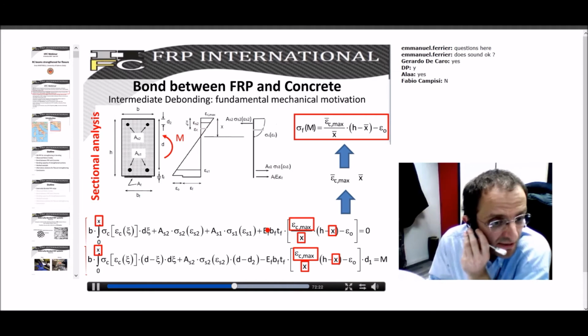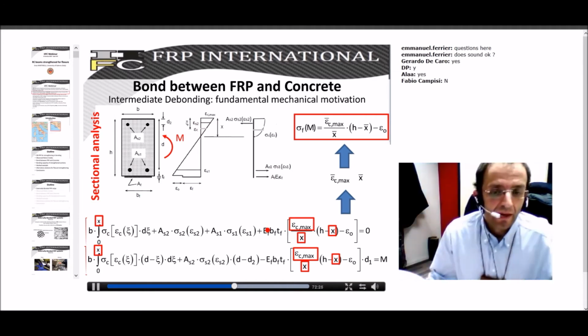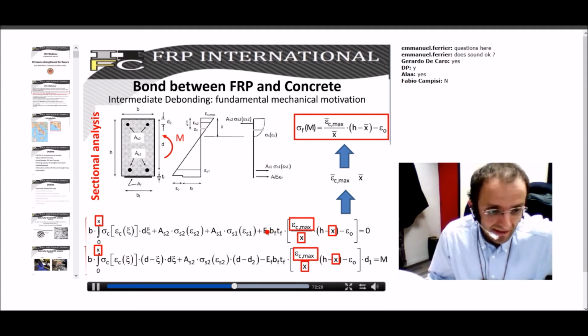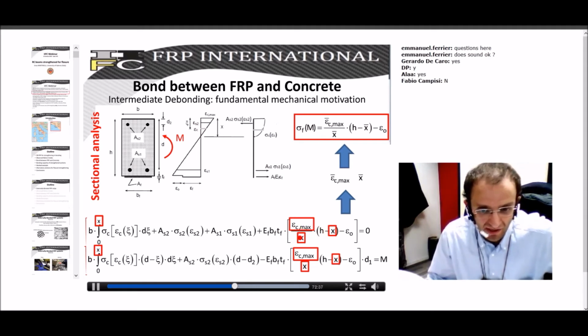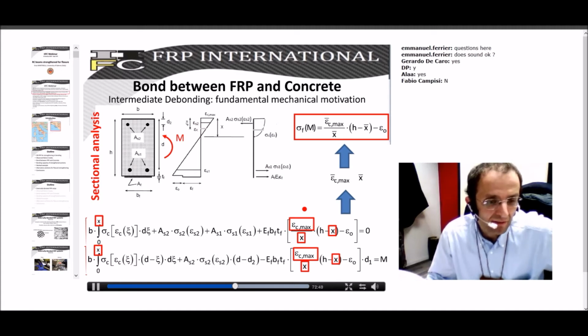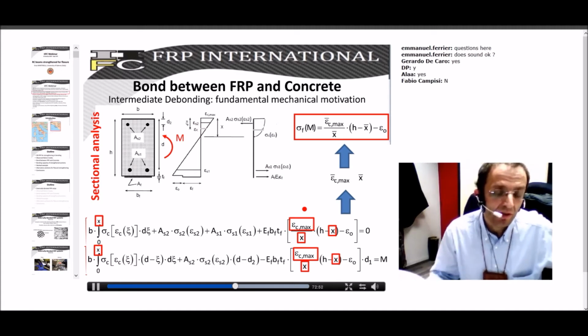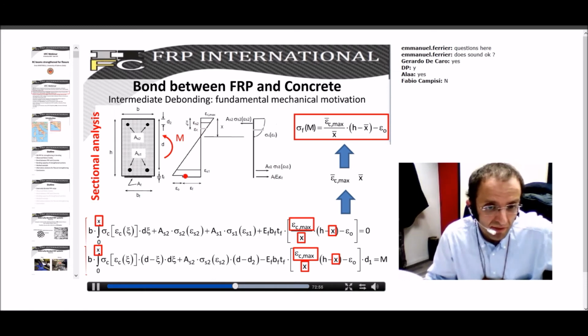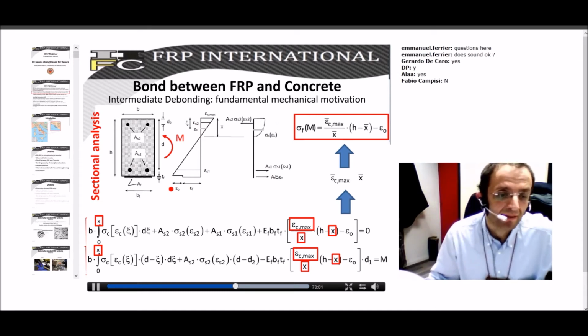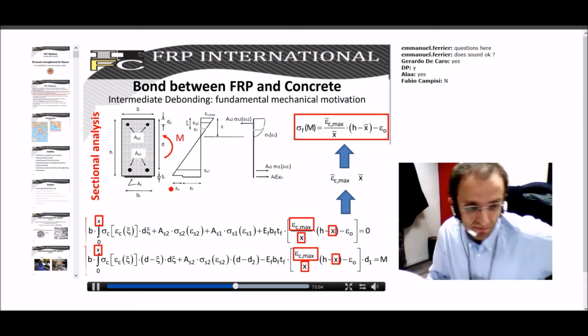Fibers are always stiff, always elastic. This means that their stress is always given by the axial stiffness times the effective axial strain, which is the axial strain potentially deriving from the conservation of plane sections minus epsilon zero, which is present at the bottom chord of the section, and then it should be subtracted, as you can see here, because the epsilon in f is lower than the one which should have been attained in the case of plane section remaining plane.